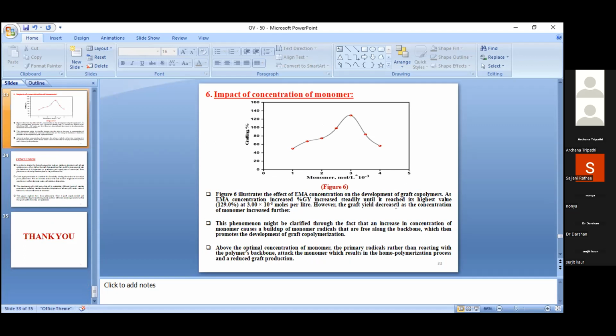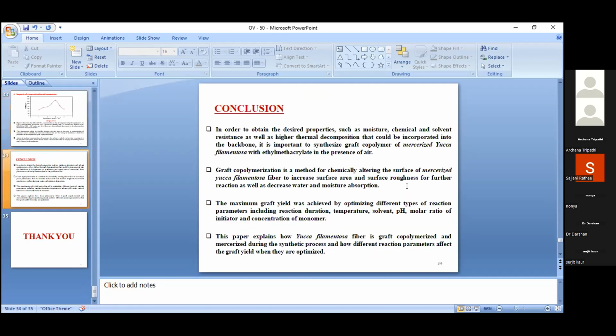This phenomenon might be clarified by the fact that an increase in concentration of monomer causes a buildup of monomer radicals that are free along the backbone, which then promote the development of graft copolymerization. Above the optimal concentration of monomer, the primary radical, rather than reacting with the polymer backbone, attacks the monomer, which results in the homopolymerization process and reduces the graft production.